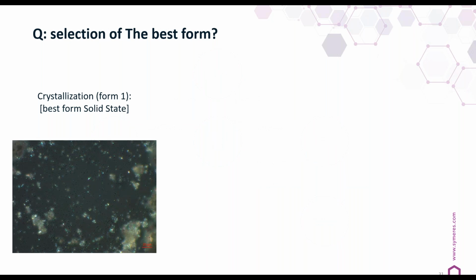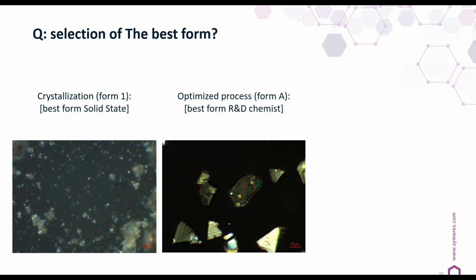Questions I get as well is, okay, how to make the selection of the best form? Here I have an example in which different companies had a look at a certain material. According to a solid state company, this crystallization of form 1 was excellent. You get a nice free-flowing powder, and the properties of that one for a solid state person were excellent. Looking at how to make your material, from a process chemist, no, absolutely not. We have these kind of nice, large crystals, filtration rate excellent, drying times very short, and you have an optimal form here. A totally different form compared to what the solid state actually has as optimal form.